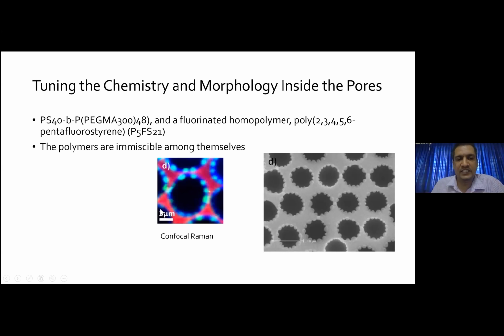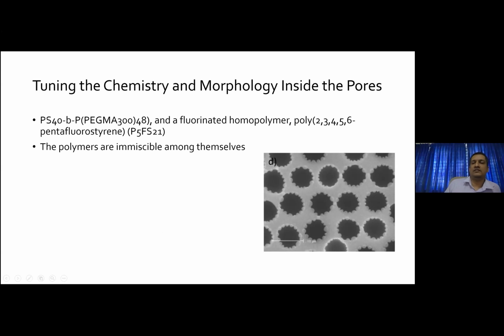have been taken in such a ratio that during the process of breath figure formation, they align in such a way that one particular type of polymer is placed wherever you want. In this case, the perfluoropolymer is of low molecular weight, and this is a diblock copolymer, and this diblock copolymer takes the major skeleton, whereas this perfluoropolymer has undergone something called thiol click at the para position.